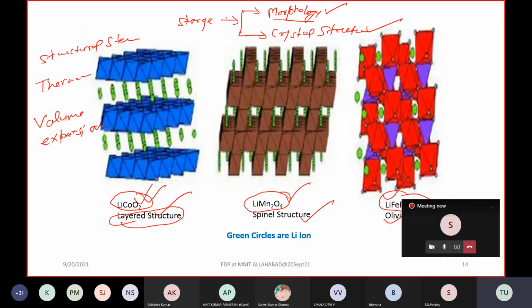If you see lithium cobalt oxide, this is good, but it is structurally and thermally unstable. So people are not avoiding its use, and it is still being used, but its utilization is not of that kind. LiMn2O4, if I talk about it, is thermally stable, but structurally it has a problem. So we are looking at making combinations of these two, by which we are going to get the best properties of both, and it could succeed for the next generation.